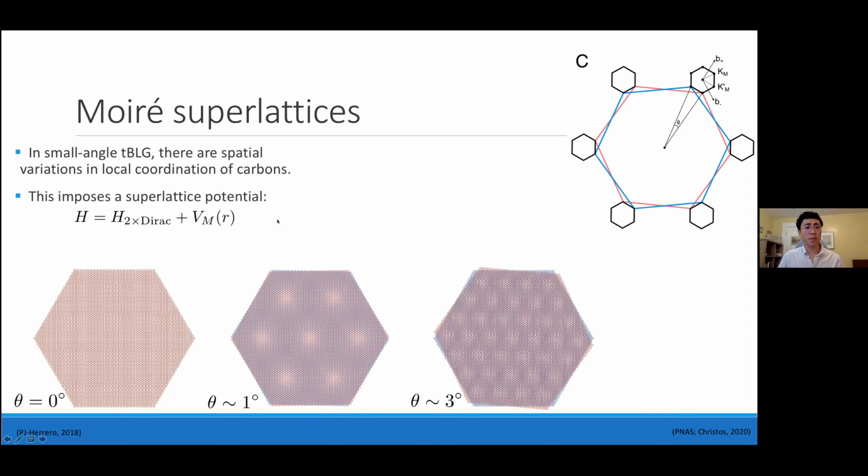And so we can describe these physics in terms of the Dirac cones of the two otherwise decoupled layers of monolayer graphene, and then a periodic potential V on the scale of the superlattice, which both has in-layer tunneling components and also crucially tunneling between the two layers.